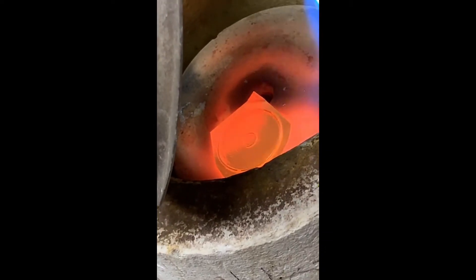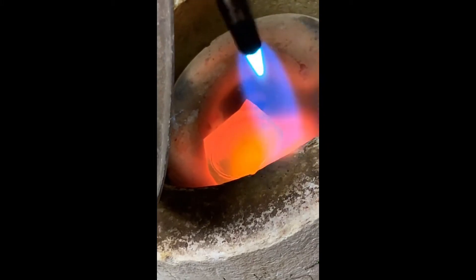Next time I want you to leave a little more back sheet rather than trimming it like that. Because having that little more room there gives me a place to be with my torch that is not your wire when I'm heating it up. It'll make it a little easier. In order to try to get that hot right there, I'm kind of having to sit on top of your wire, which I don't really want to do. Because the wire's heating up faster — it's not attached yet, and while it's not attached, it's smaller than everything else.